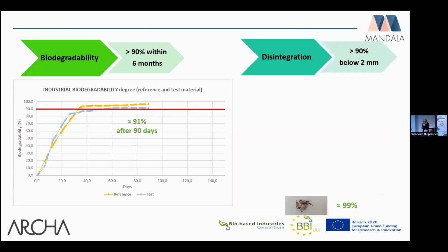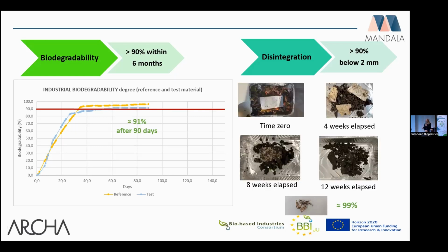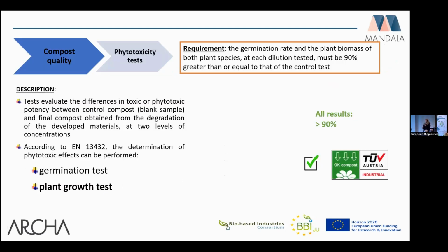And what we obtained was about 90% at the plateau level after 90 days of industrial biodegradation percentage of the formulation. So this is, sorry, the animation doesn't work. I can go on with the next one. Okay. For biodegradation, it is compliant with the requirement. And for disintegration, the same, since we achieved more or less 99% of material below 2 millimeters in dimension after 12 weeks.